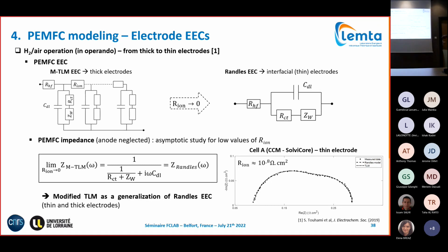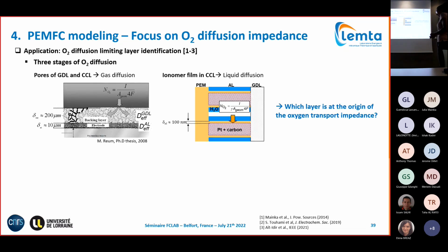Here is a spectrum measured on a commercial cell with thin electrodes. Here you see the fitting curves of your Randles model and of your TLM. And we see we have identical fitting curves. So this validates the validity and applicability of our modified TLM.